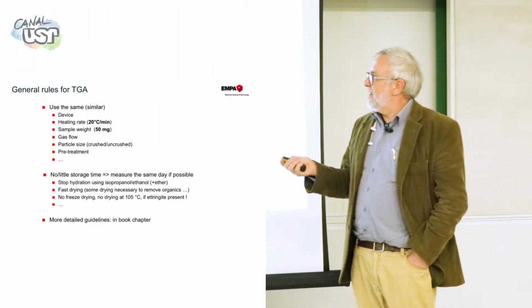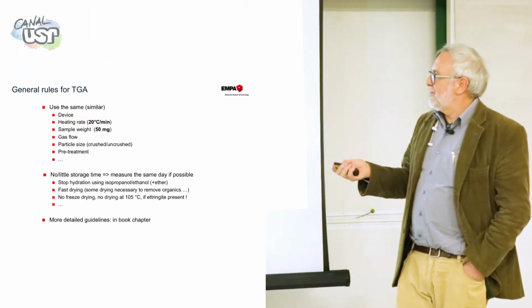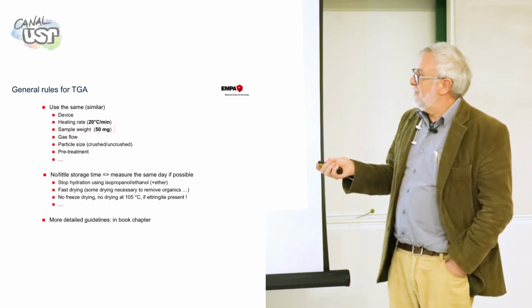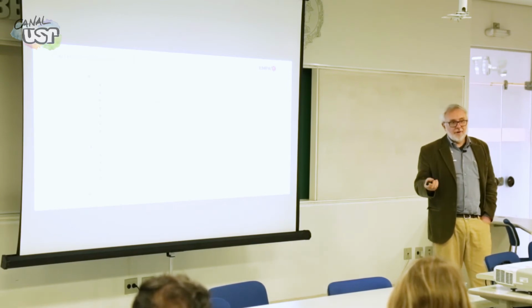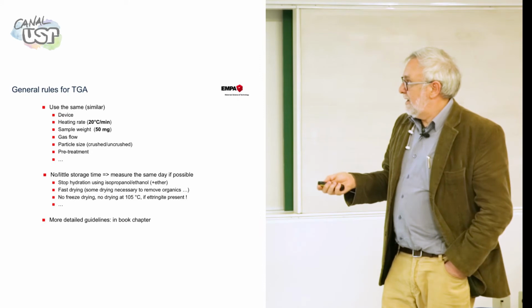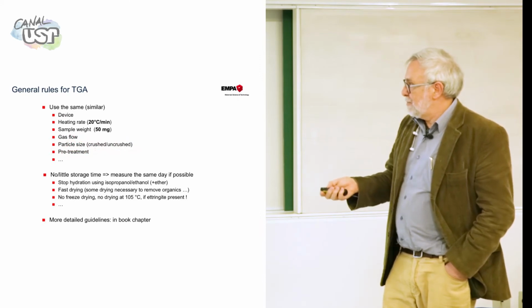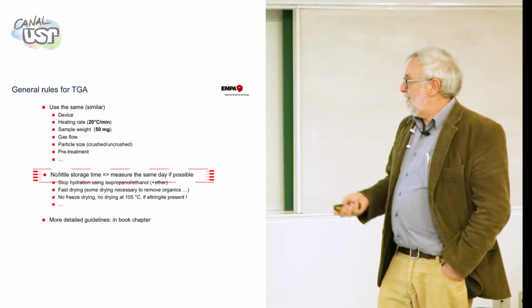Recommendations: use the same device, same heating rate. We use 10, you can use 20. Sample weight, 50 milligrams, I think it's good, depending on your thermal balance. If you really want to see an admixture in it, the organic decomposition of an admixture, you are going to need 1 gram. And we have a balance for that with 1 gram. You can see the grinding admixture that they put in the cement to ease the grinding, to reduce the energy. You can see it inside. Gas flow, particle size, pretreatment. Storage time you have to reduce.